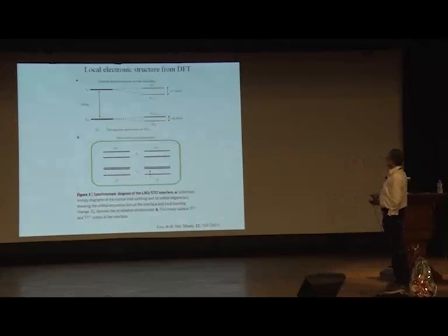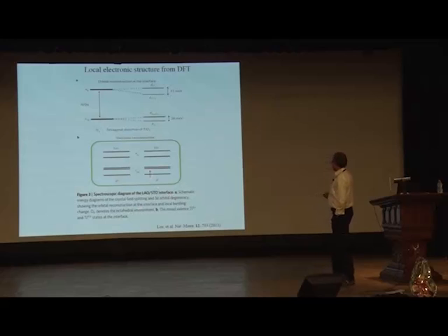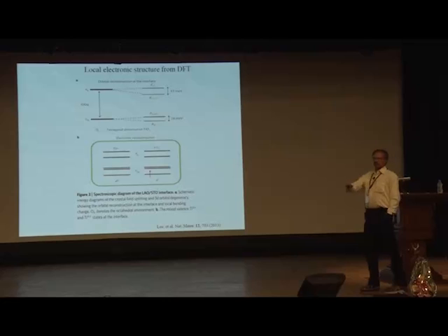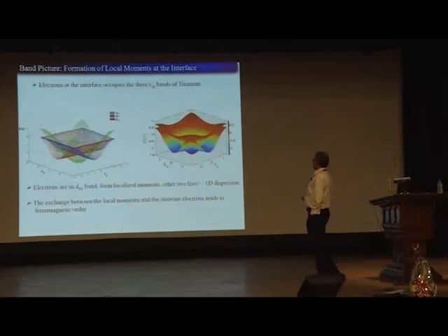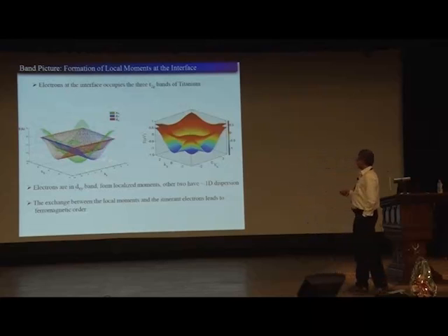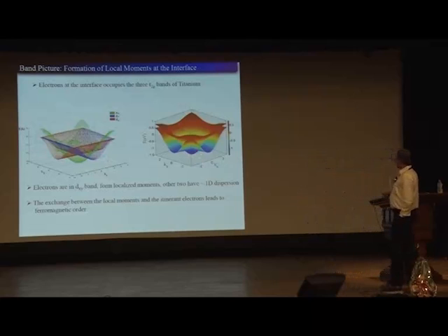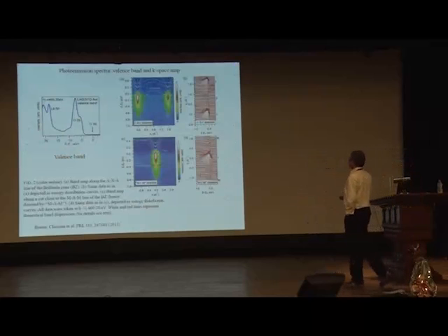Okay, so this is the simplest electronic structure one can think of. This is proposed by Lee, and so there's a d1 Ti3+. So there's a d1 electron, and that has to go to this d_xy, which is the only one which is sort of free in 2 dimensions. So this is the one. This d_xy band is stabilized by just simply Heisenberg uncertainty because it has no z extent. These other ones are 1 dimensional. So that's it. Okay, so let me skip it.